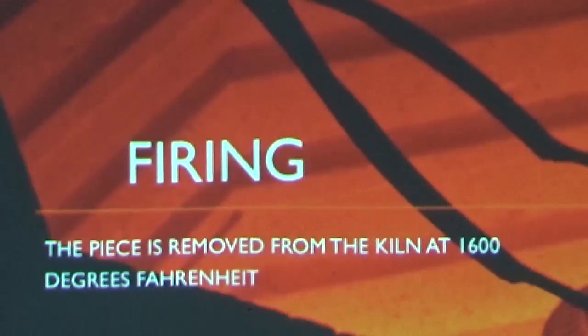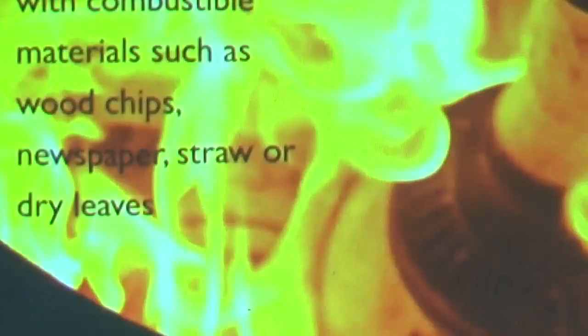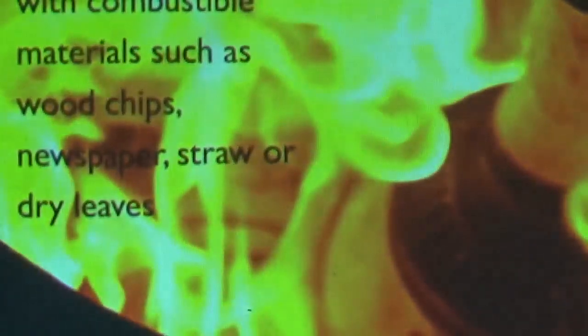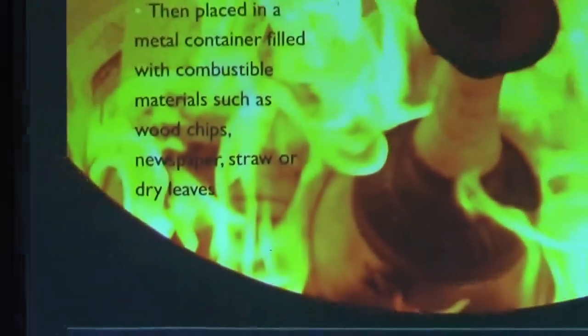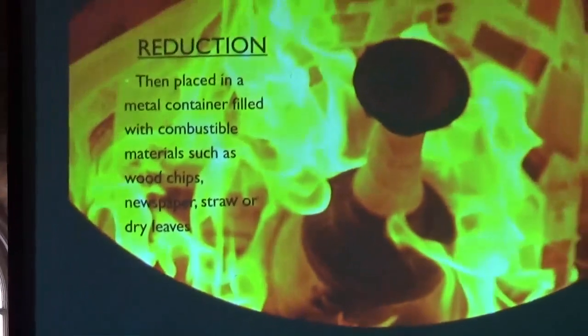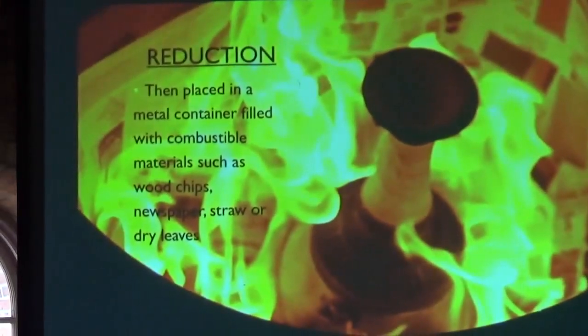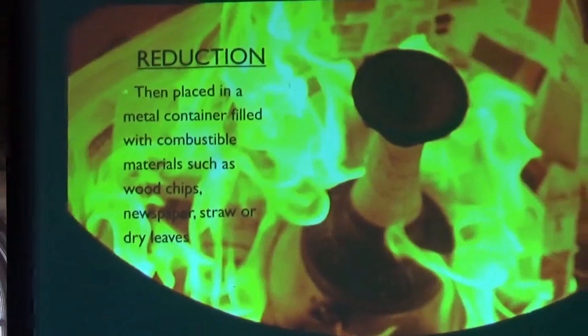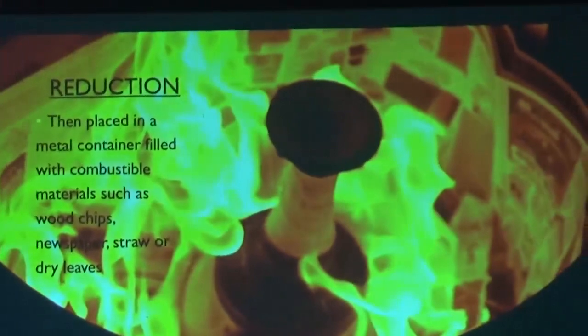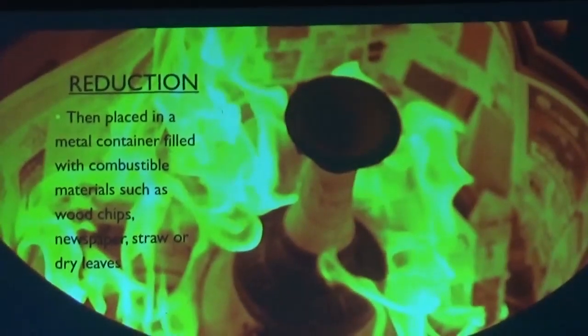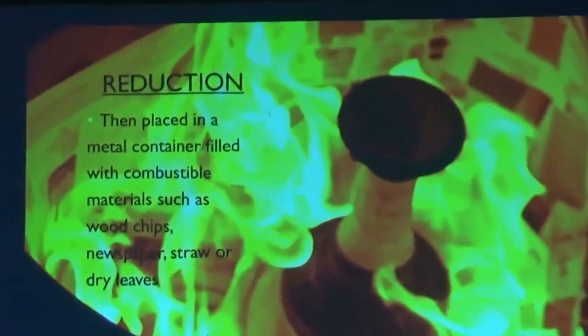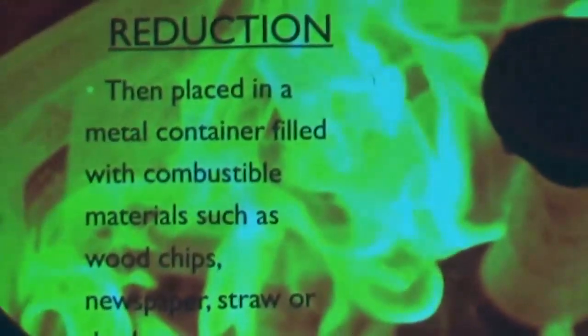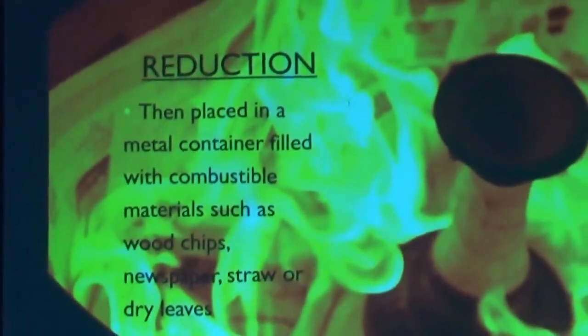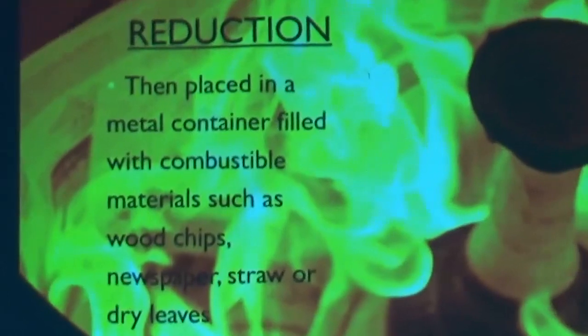So it's plucked from the kiln, hot, and put into this barrel where everything immediately lights on fire. Obviously, the flash point of paper is 451 degrees, and this is almost four times that, so it comes alight immediately. Once it comes alight, I let it burn for a second, get a really good smoldering fire going, and then it's immediately covered up. And that creates the reduction environment, the lack of oxygen.